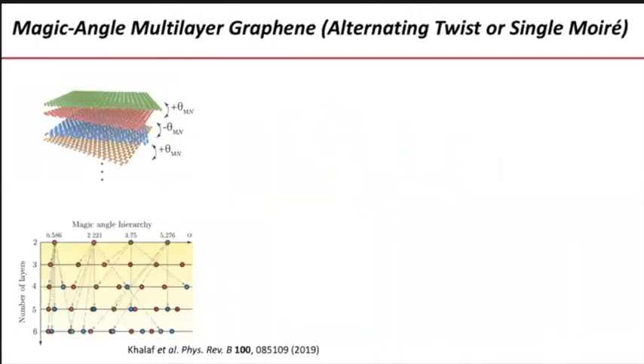So this construction of trying to get flat bands by twisting graphene layers was generalized by the group of Ashvin Vishwanath in 2019. Turns out there is something you can call magic-angle multilayer graphene, with an alternating twist structure where you put consecutive layers on top of each other with an angle theta, minus theta, theta, minus theta, and you go like that. So there is a single twist angle, or single Moiré pattern. And here you have the number of layers versus the magic-angle hierarchy. This parameter alpha goes as one over the twist angle.